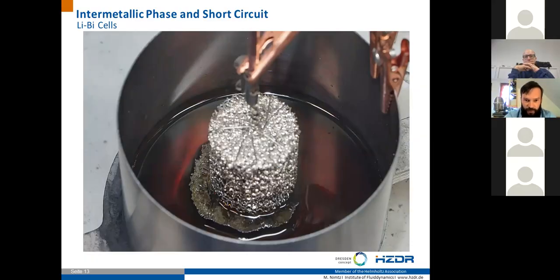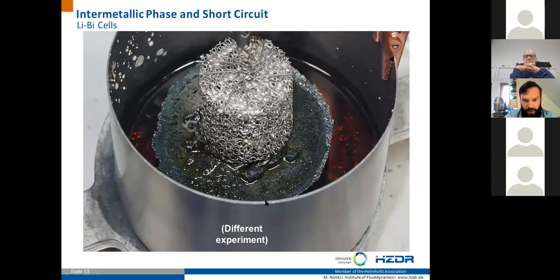And if the color occurs here, there is a high chance that you formed the intermetallic phase in large amounts. Here we can see this gray-green disk formed directly at the bottom of the electrode. And here we can see almost all the lithium in another experiment. All the lithium from the nickel foam has reacted with the bismuth and formed a large intermetallic plate. And this is something nearly impossible to remove, especially if you operate the cell in a closed crucible.